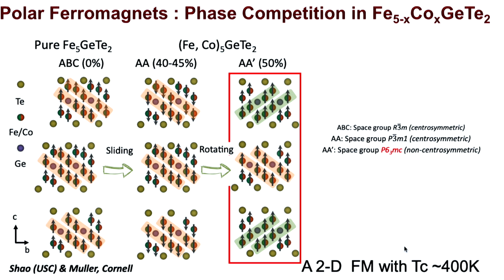At 0% cobalt, it has this centrosymmetric ABC structure. All the way up to about 50% cobalt, it is centrosymmetric in the so-called AA structure. But right at 50%, it starts to go into this AA prime structure, which breaks inversion symmetry. And these materials are ferromagnetic with the TC well above room temperature. They also break inversion symmetry. Formally, they're multiferroics. Of course, these are metallic systems. So these are formally polar metallic ferromagnets.